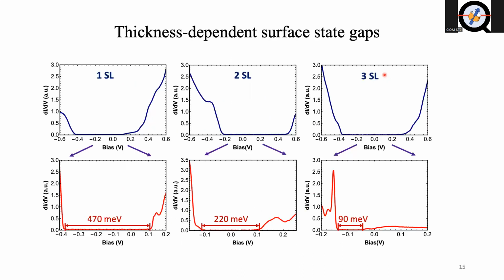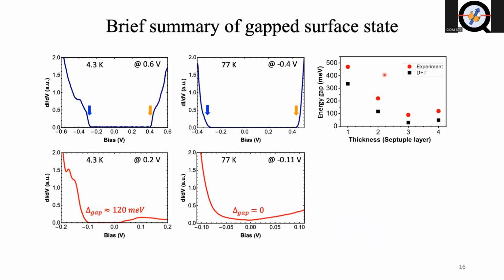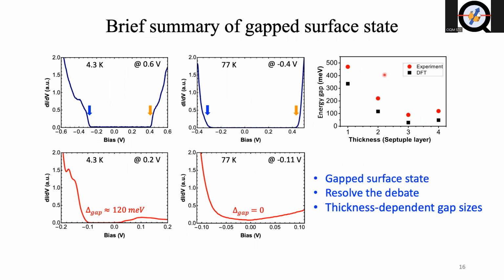Similarly, we did the thickness dependent surface state gap measurement on different septuple layers or thicknesses, and we can summarize it here as below. Together with our DFT calculated result, which shows a good overall agreement, given the tendency that DFT usually will underestimate the gap size, overall they agree pretty well. So yeah, a very brief summary: upon having a nice sample, meaning that we can really eliminate the amount of defects and move the Fermi level to be within the gap, we observe a clean gapped surface state, and we resolve this hot debate in the field. And we also carried out a thickness dependent gap size measurement.